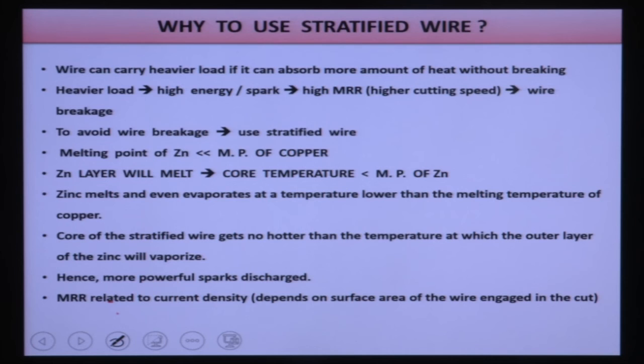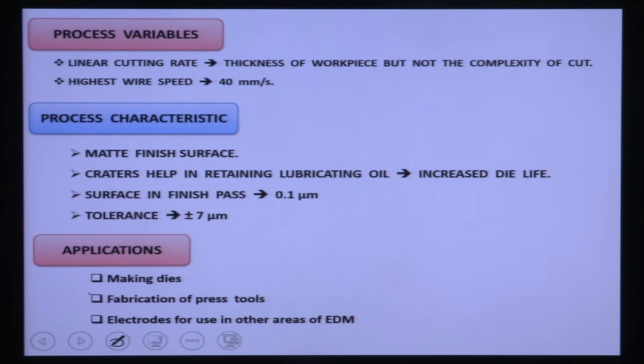So during machining, during sparking, the outside zinc layer will melt, but the core temperature does not reach the melting point of copper. Zinc melts and even evaporates at a temperature lower than the melting temperature of copper. So the core of the stratified wire gets no hotter than the temperature at which the outer zinc layer vaporizes. It does not break, hence more powerful sparks can be discharged. MRR is related to the current density. As the wire diameter reduces, the current density will also be high, so you can generate high energy per spark, and your material removal rate will be high without breakage of the wire. Charmilles Corporation developed this kind of stratified wire, and it is also not reused.